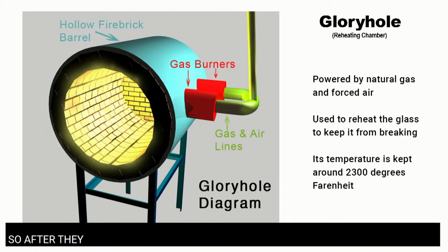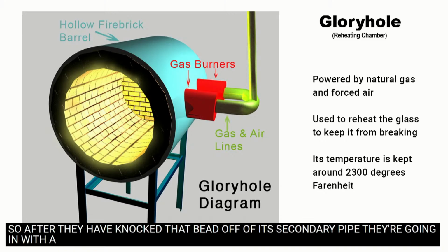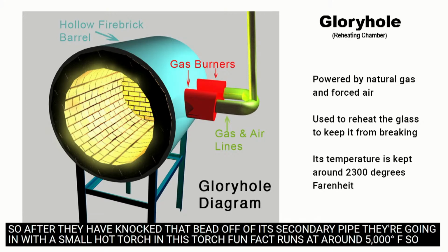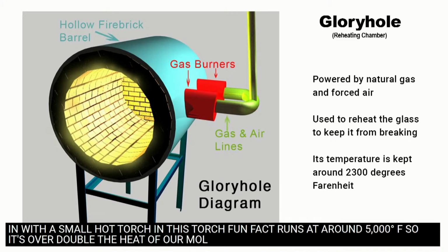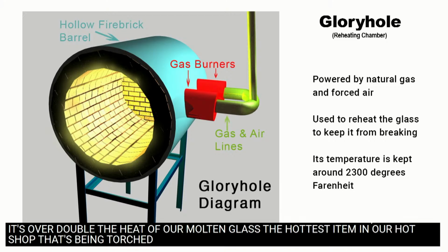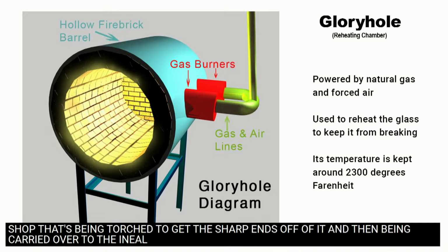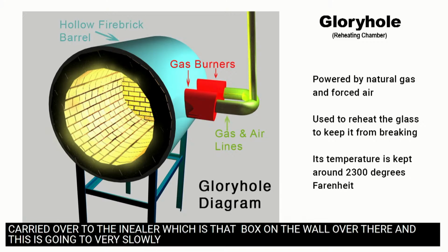So after they've knocked that bead off of its secondary pipe, they're going in with a small hot torch. And this torch, fun fact, runs at around 5,000 degrees Fahrenheit, so it's over double the heat of our molten glass, the hottest item in our hot shop. That's being torched to get the sharp ends off of it, and then being carried over to the annealer, which is that big black box on the wall over there. And this is going to very slowly cool our piece down so that it doesn't break due to thermal shock.